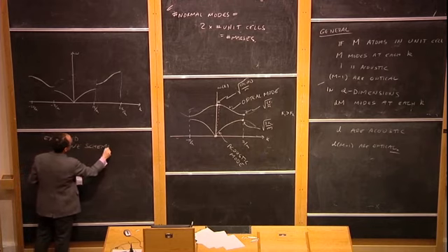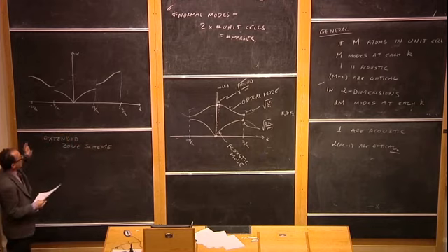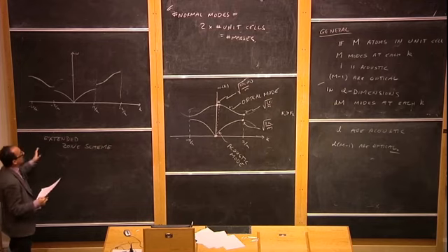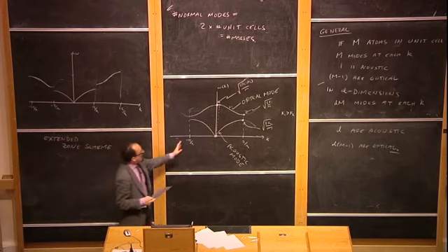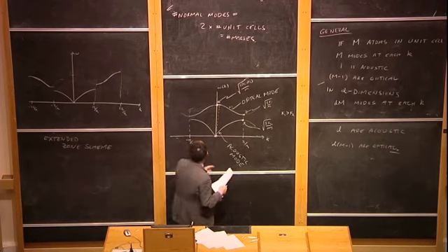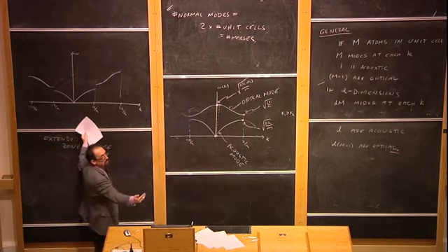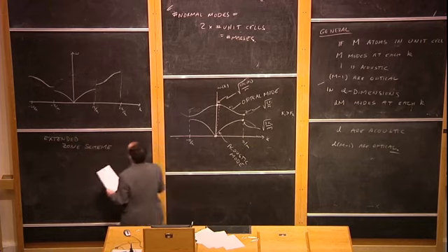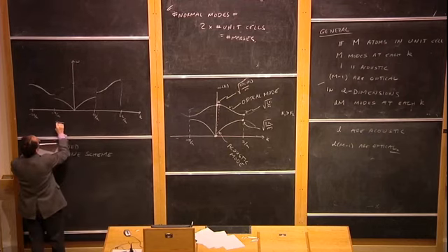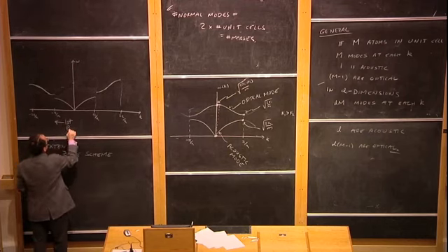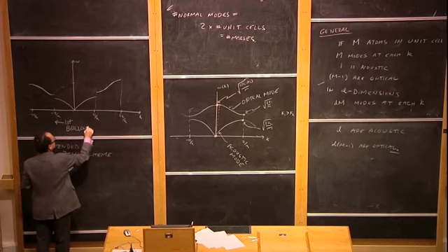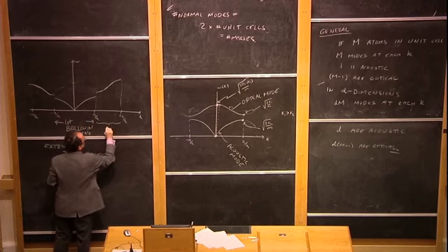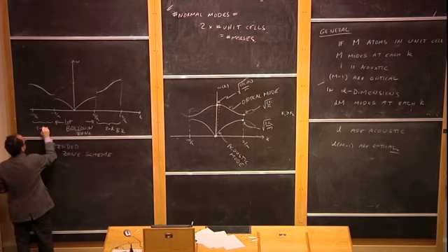And it has a nice advantage that there is only one mode at each frequency, at each wave vector k. So whereas over here we have 2 modes at each wave vector k, here we only have 1, but we've used twice as much range of k, and that's sometimes convenient to do. Just some nomenclature which is useful. This range here is known as the first Brillouin zone. And this region here is known as the second Brillouin zone, along with this region here, second Brillouin zone.